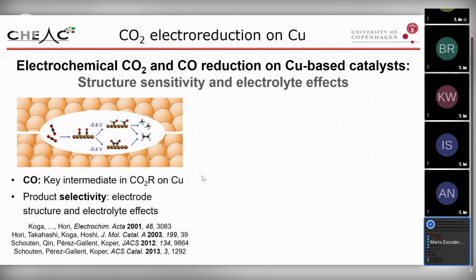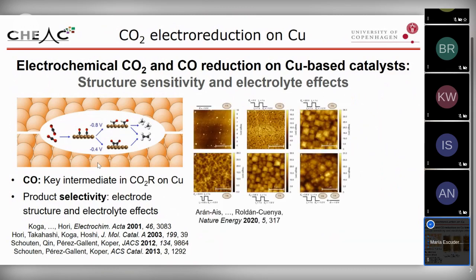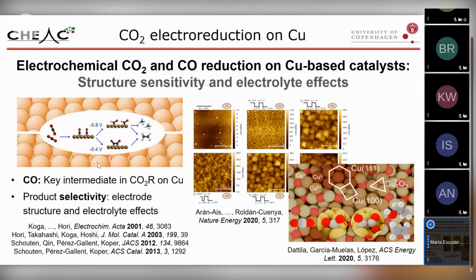As Beatriz also introduced, CO reduction is structure sensitive, and the product selectivity will depend on the structure of the electrode and also on electrolyte effects. Given that CO is the key intermediate for the reduction of CO2 on copper, it is also, for some types of measurements, easier to investigate CO reduction in order to gain insight into the mechanism of this reaction. As we saw before from Beatriz's group, it is really important to be able to control the structure of our catalyst, and the different structures will change the product selectivity.